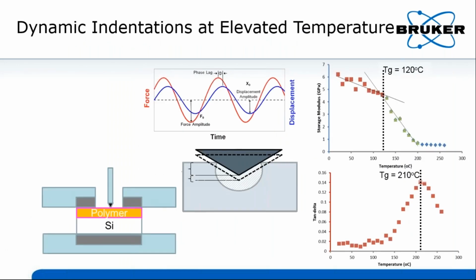However, in case of the thin film, nano DMA could be of much help since the sample can be put directly in the heating stage to make dynamic indents on it. Let's go to an example to show how nano DMA is working for thin films. Here we demonstrate the Tg measurement results, and the sample is a 1 micron polymer film on silicon substrate. DMA indentations were applied to the sample in order to collect the storage modulus and tan delta varying with temperature. And the heating stage was used for controlling the sample temperature from room temperature to 260 degrees Celsius.